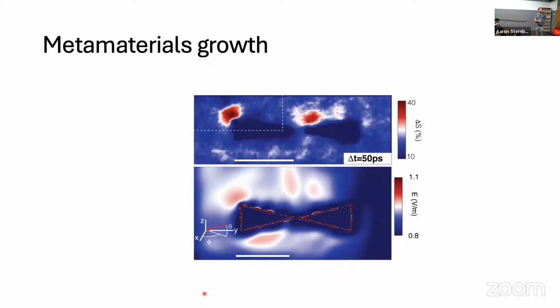The last thing that I wanted to stress is that if you put structures on your film, you change the magnitude of the local electric field, in some cases by a lot. In the terahertz, this can again be factors of 1,000, 10,000. Even in the infrared, we can get modest field enhancement of about 50%. And this field enhancement was actually sufficient to drive metallic nucleation to occur at specific sites near the corners of resonators that we patterned on our film.